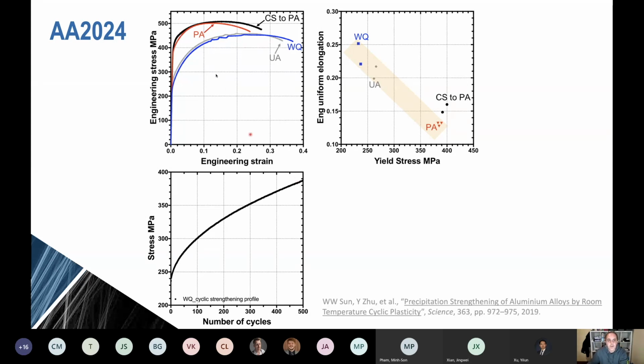And so it's quite remarkable. This is the black curve, CS, which we've referred to as cyclically strengthened. That is the stress strain curve from a water quenched sample that has been cycled about 500 times at room temperature, and we can see we end up with a yield strength that's at least as strong or even higher than the peak age state and a better uniform elongation. What this shows us, and it's not a surprise that we can have dynamic precipitation in something like aluminium, but it's a surprise that the tensile properties can be so good that they exceed those of the peak age T6 state.